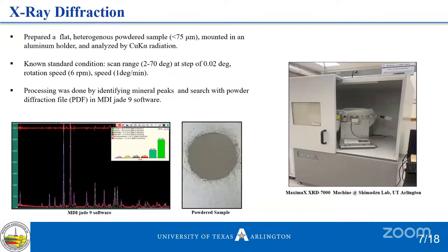So for example, for the XRD, this is available in the university. We have this, and this is one of the latest ones we have. The quantitative mineralogical analysis is usually performed on ray cuttings or even crushed core using X-ray XRD in combination with other measurements such as analysis of the bulk elements, particle and bulk densities, which I had to compute for each of these samples. And the most important thing is that you have to grind the cores and the ray cuttings to powder sample size.